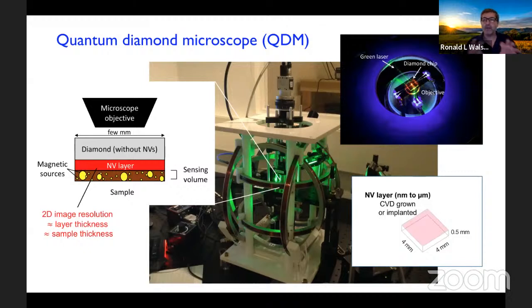Why? Because if the sample features are 2 or 3 microns, you're not going to get any better spatial resolution than that in any case, because the magnetic fields from them will blur out any higher resolution image. And if you make your NV layer thicker, you get more signal and you can get better sensitivity. So the rule of thumb is to make your NV layer thickness about the same as the sample thickness. What if your sample is only a few hundred nanometers thick? Then you might do the same sort of thing with your NV layer and be limited by the optical diffraction limit. So different diamonds with different thicknesses of NV layers are used for different applications. So we have a bunch of different diamonds and we use them for different applications, which I'm about to start outlining for you, but it's the same basic setup.